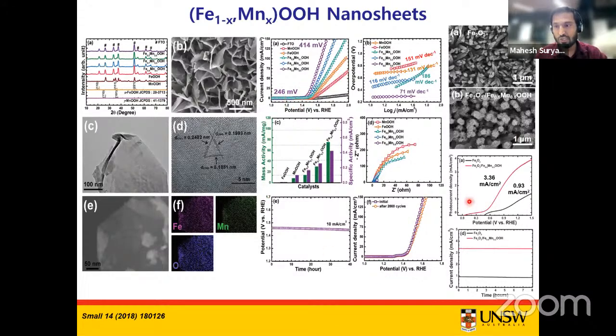After loading this catalyst on the photoanode, that is Fe2O3, because we wanted to create a photoanode system comprising all earth abundant metals, that is Fe. We chose Fe2O3 again because of its suitable band gap as well. There is an improvement in the photocurrent density to about 3.36 milliampere per centimeter square, which is a significant improvement after this catalyst loading. If you see the stability plot, you will understand that even after a stability test of several hours, the photocurrent density of this photoanode is almost similar, and that suggests the role of this catalyst in stabilizing the photoanode materials as well as improving their performance.